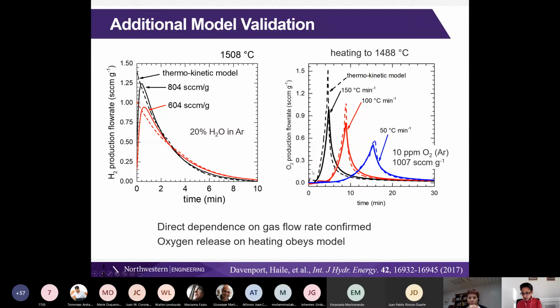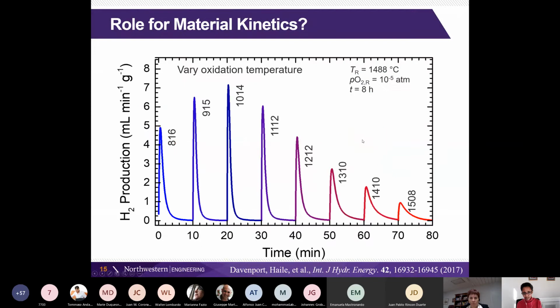We can simulate also the heating profiles. That means just updating the temperature each time in our calculation. And when we heat very quickly, the reactor, in fact, is a little bit behind, or the thermal diffusion through the material is a little bit behind. So we're not quite as high as our thermokinetic model, but at a moderate heating rate of 50 C per minute, we match well. So all of this tells us that this model is valid. So is there ever a role for material kinetics? And the answer, of course, is yes.